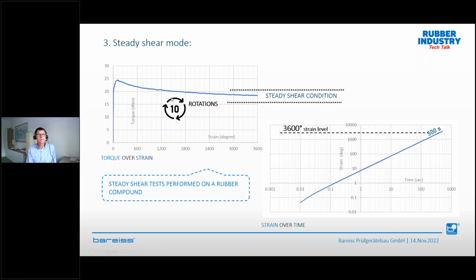And then, for example, here are 10 rotations. You put a compound in, and then we measure the torque as a function of time or degree. So when we make 10 rotations, we have 3,600 degrees of arc, because 360 multiplied by 10. And you see we have this small overshoot, and then we are going more and more into a flat condition. Yeah, that's very important information here. So how does it look on our motor? Well, the motor starts rotating from 0 to 3,600 degrees, 10 rotations, in, for example, 500 seconds.